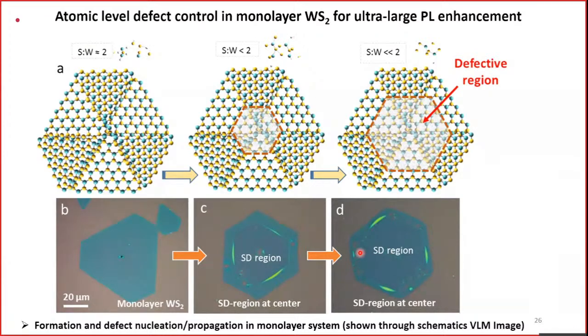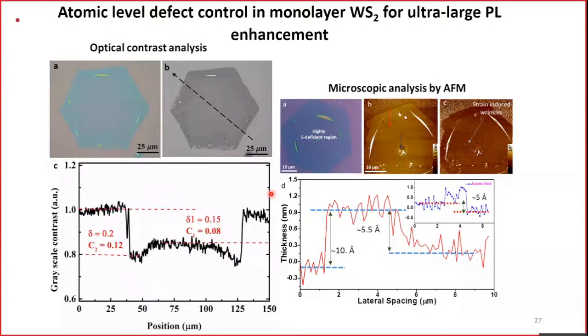So like I was just trying to explain, when we have a deprived condition, when we have a small amount of sulfur precursor available for the growth, we end up creating a heavily, or severely, sulfur deficient region at the center. We want to see how this sulfur deficient region is going to contribute to or affect the properties. Again, the sulfur deficiency can even be seen in the optical contrast. You see in the monolayer there is a difference in the optical contrast. We also looked at the AFM, though it is very close to the measurement limit of the AFM. We do see some difference in the height. Compared to the side, in the center the height is also lower, indicating that some removal has taken place.